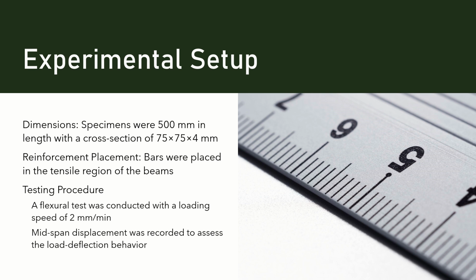Let's look at the details of our experimental setup. The dimensions of the specimens were 500 mm long with a cross section of 75 by 75 by 4 millimeters. We placed the reinforcing bars in the tensile region of the beams. During the test, the load was applied at the speed of 2 mm per minute.